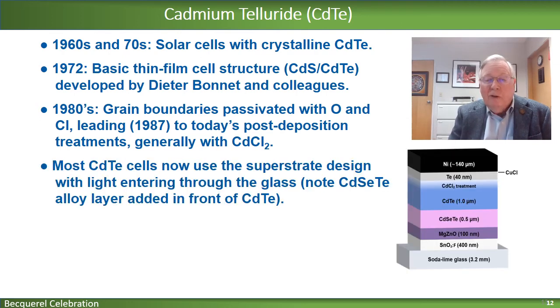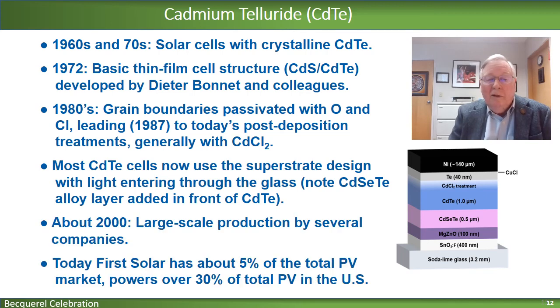Most cadmium telluride cells now use the superstrate design, which I showed earlier. And in this case, the light enters through the glass. Note that you have to flip it over in order for the sun to shine in the right way. And also this layer of the alloy of cadmium selenium telluride has become quite common. So about 2000, the large-scale production by several companies of cadmium telluride got underway. And today, First Solar has about 5% of the total photovoltaic market. But in the US, it's powering well over 30% of the total photovoltaic electricity being generated.